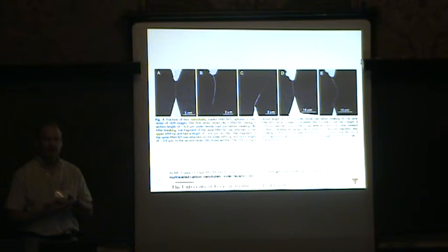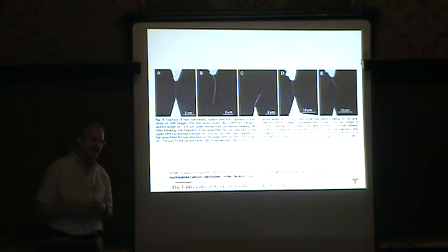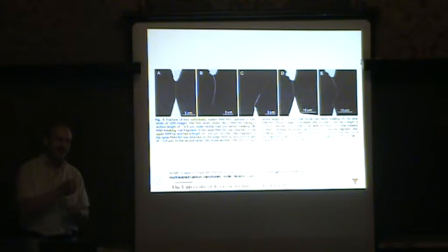So you can see this bright to dark transition here. This is where the outer shell broke. And we end up in situations where we had this sort of snake-like appearance after the bottom cantilever would relax, and then the upper cantilever would pull the shells apart. So later I'm going to tell you this kind of fascinating shell-sliding experiment, and the mechanics of two nested shells where you can fracture the outer shell, and you're sliding the outer shell with respect to the inner shell.